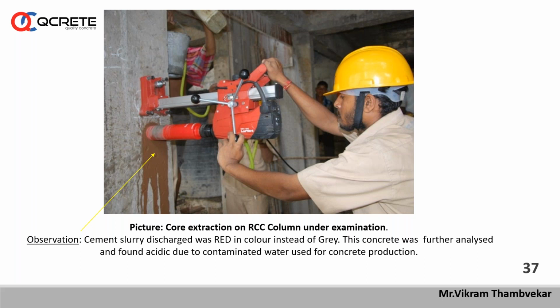This is the one thing. And the second thing, the water used to make this concrete was not proper. How we judged it: because the cube failed, thereafter we tested all this. The hammer test was not satisfactory. UPV was good, but again the core test was also not proper. In the core test also we were getting very less strength. Then one day this contractor came to us with some other cubes, not of the same concrete, and they said, don't tell your sir that these are different cubes. Then I came to know there was something wrong. We again took cores from all these columns, and we found again the strength was very less.